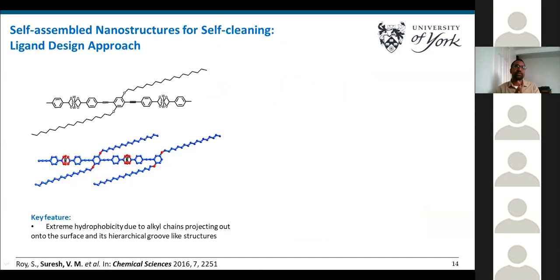We have extended this system also to self-cleaning application. Here you see, we have used the same metal ion, which is zinc, like the previous system, but the length of the alkyl chain we have increased to C18 compared to the previous system, which is only C8. So the idea is to create a self-cleaning or superhydrophobic system. So it makes sense to increase the length of the alkyl chain.